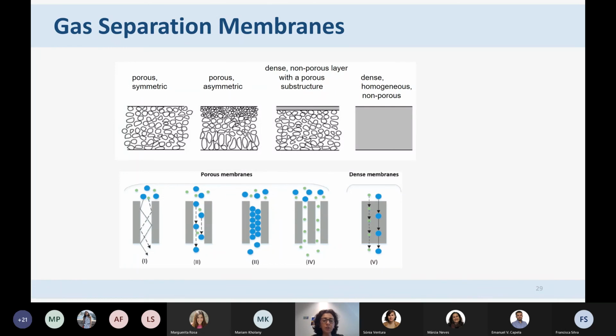Shall I have it dense and non-porous? Shall I have it completely porous? So we evolved from the dense, and now we are here, because we cannot do porous symmetric membranes starting from polymers, because all the gases have very much the same kinetic diameter. And so it is very difficult to produce porous membranes that have different pore sizes to differentiate between the gases.